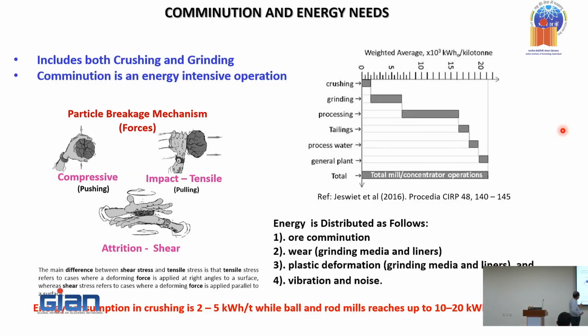Now when you look at it, energy consumption in crushing is about 2 to 5 kilowatt hours per ton, while grinding means further size reduction. In the case of crushing, there is the reduction ratio, which means feed size to discharge size. It is about 3 to 5 at most. But when you go to grinding, it may be much more. It is not actually defined because it will be extremely high, more than 100, more than 200, or it may be more than 1000 also, depending upon the mineral property. Therefore, in ball and rod mills, which are conventionally used for grinding, the consumption of energy is 10 to 20 kilowatt hours per ton.